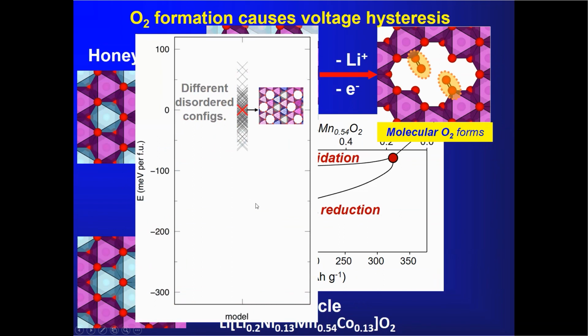Now, just to show you some DFT work looking at the energetics of some of these processes, what you see is the energy of different configurations here. And here the red cross represents the energy of our honeycomb, our ground state, if you like, our pristine material, and here are the vacancies. And so these gray crosses represent exploring different configurations for the various vacancies that you see here. And of course, you get a range of energies as you arrange these vacancies in different disordered configurations.